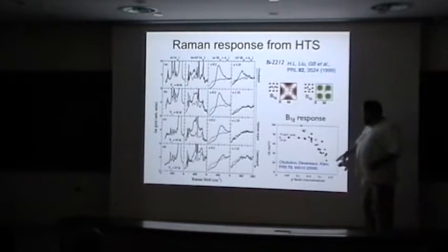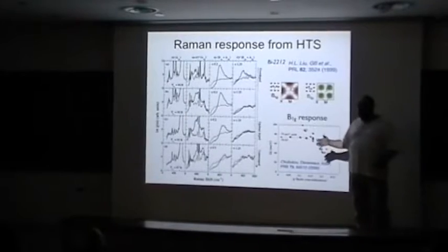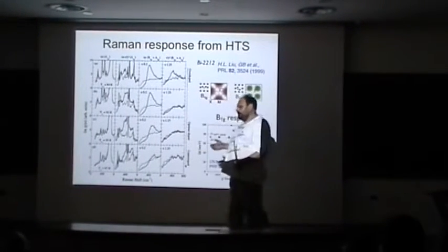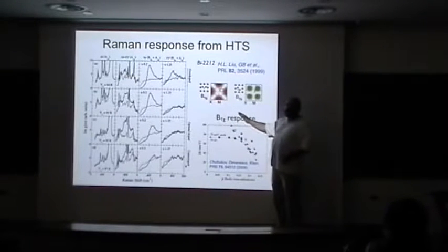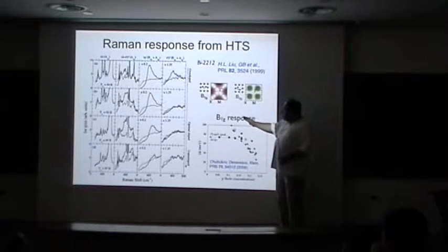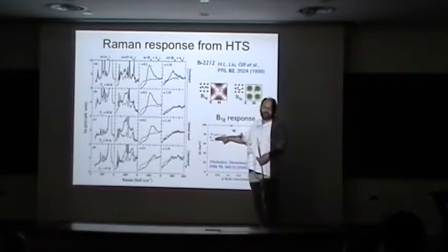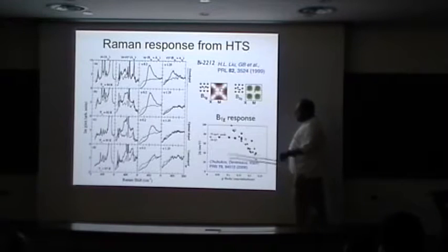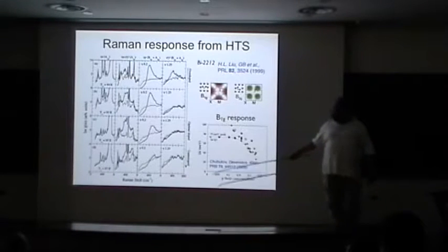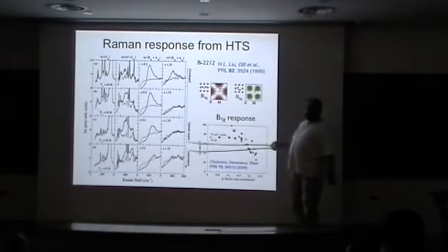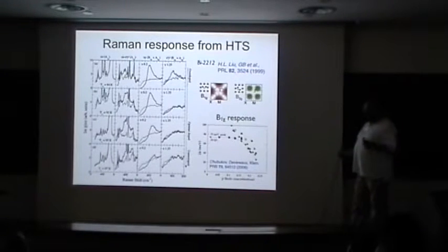It's shown in this paper that if the coupling is in the charge channel, or basically the phononic channel, this mode will be pushed into the continuum and we shouldn't see it. In contrast, if the coupling is in the magnetic channel, then the energy should be lowered and we should see it. So one can take this data as a proof that the coupling in high Tc, well, at least in Bi-2212, is due to some kind of magnetic interaction. So the boson has magnetic origin.